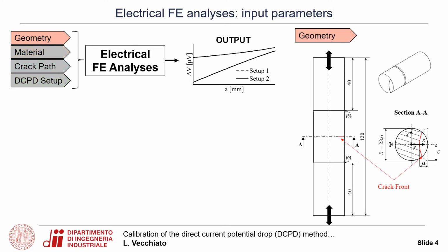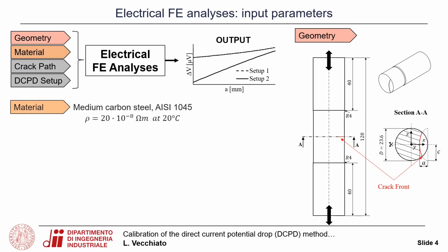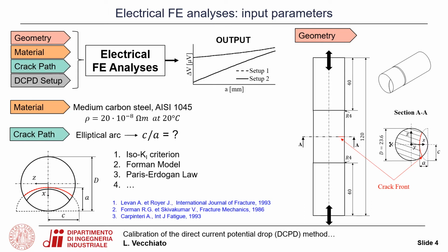In this work, a cylindrical specimen with a semi-elliptical edge crack has been studied, and the material was chosen to be equal to a medium carbon steel with an electrical resistivity of 20 times 10 to the power of -8 ohm meter at 20°C. About the crack path, according to the literature, it has been assumed the crack propagates with a semi-elliptical arc shape.